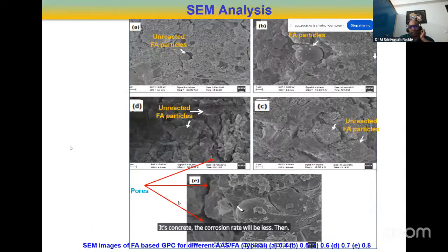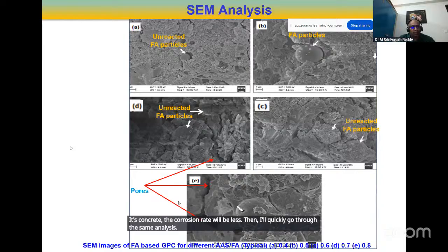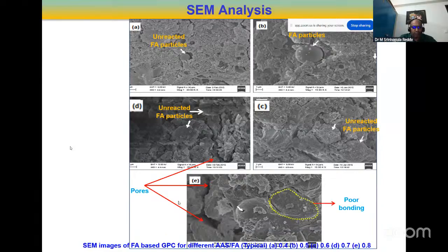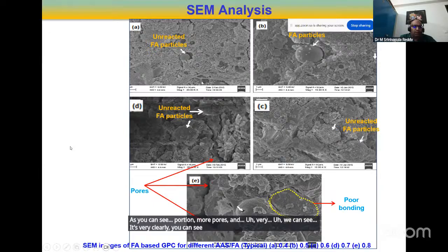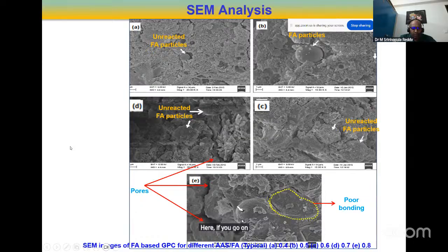Then I will quickly go to the SEM analysis. Here you can see pores, more pores, and very clearly you can see a crack type of structure. If you go on increasing the AAS/FA ratio, because of the poor bonding, some unreacted particles, you can notice here, and you can see these pores.